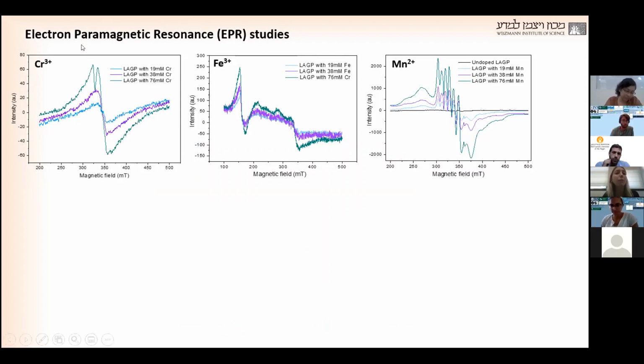We also want to show that we have the paramagnetic ions inside of the LAGP. So we recorded electron paramagnetic resonance, as we can see here. And we see here in the line in black, which represents the undoped LAGP, that we didn't get an EPR signal. But when we dope the LAGP with chromium, iron, and manganese, we get this EPR signal, as we see here. And when we increase the doping from 19 to 76, we also increase the EPR signal. So we successfully showed that we have unpaired electrons inside of the LAGP. We have these paramagnetic metal ions inside of the LAGP.